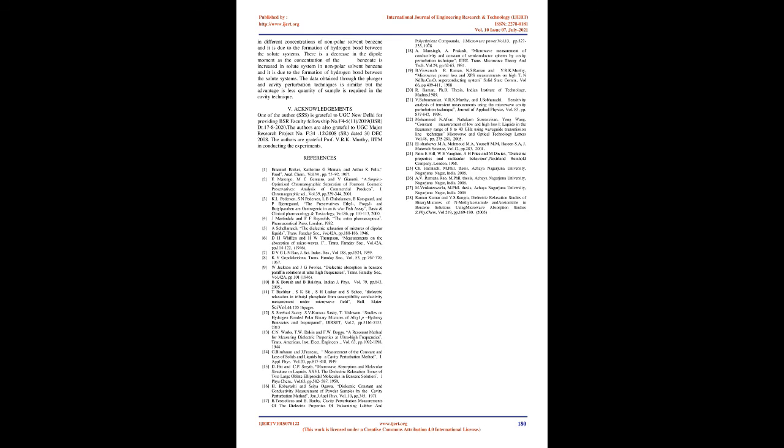There is an increase in the relaxation time as the concentration of the benzoate is increased in the solute system in different concentrations of nonpolar solvent benzene, and it is due to the formation of hydrogen bond between the solute systems. There is a decrease in the dipole moment as the concentration of the benzoate is increased in the solute system in nonpolar solvent benzene, and it is due to the formation of hydrogen bond between the solute systems. The data obtained through the plunger and cavity perturbation techniques is similar, but the advantage is that a smaller quantity of sample is required in the cavity technique.